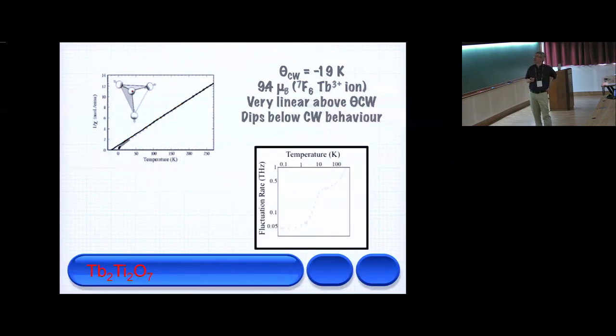And going back to my first love, terbium titanate, this has a minus 20 Kelvin Curie-Weiss temperature and a large moment. And with this system, down to half a Kelvin in susceptibility, there was no ordering. Around 50 Kelvin, there seems to be a separation from Curie-Weiss law. If you use muons, you see these persistent spin dynamics down to, I think it was 10 millikelvin we got to in this experiment. So there's obviously something going on here, which we determined in the end was a low-lying crystal field depopulating.